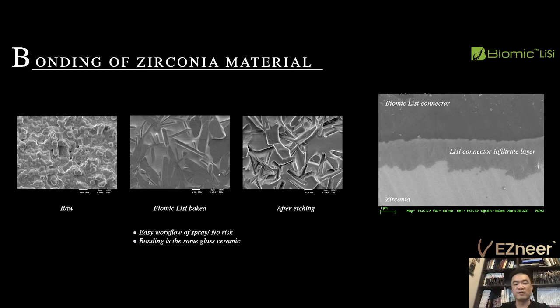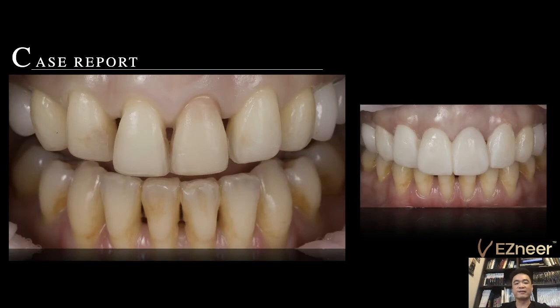So you can see this is the raw material on the zirconia surface, and after this we apply the Biomic Lisi connector, and after the connector is etched, you can see the SEM photo. It looks like silicate and the glass ceramic surface. So this is interesting, an easy workflow with no risk, and we can also get a very strong bonding strength, the same as glass ceramic with natural teeth. And this is the case report.